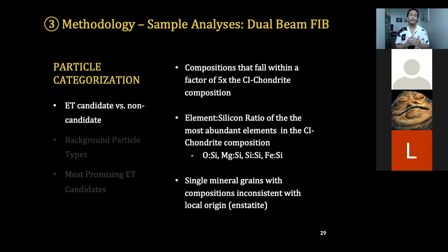The reason for the high factor number of 5 is so that we don't exclude any particles due to uncertainties caused by physical overlap of the grains in our samples. What we did was we took the element to silicon ratio of the most abundant elements in the CI chondrite composition, and that includes oxygen, magnesium, silicon, and iron. Obviously, the silicon to silicon ratio will just be 1 for all of our candidates, so we didn't look at that. We focused on the oxygen to silicon, magnesium to silicon, and iron to silicon ratios. If all those 3 ratios fall within a factor of 5 of the CI chondrite composition ratios, then we flag that as a potential ET candidate for further analysis.